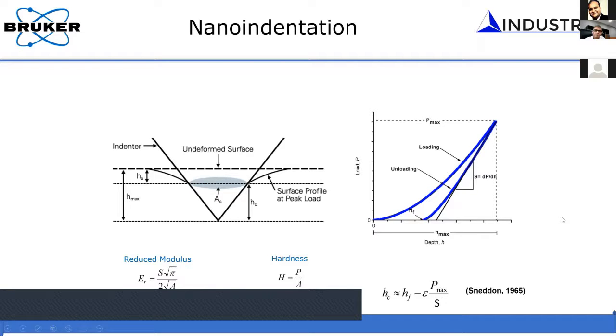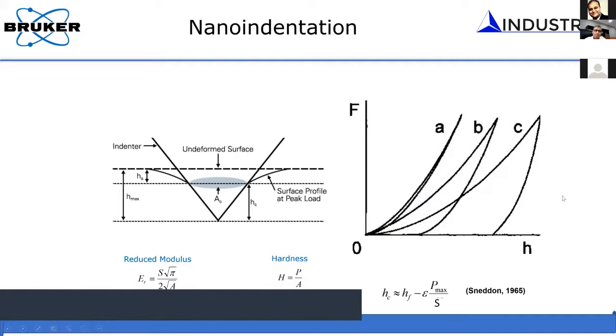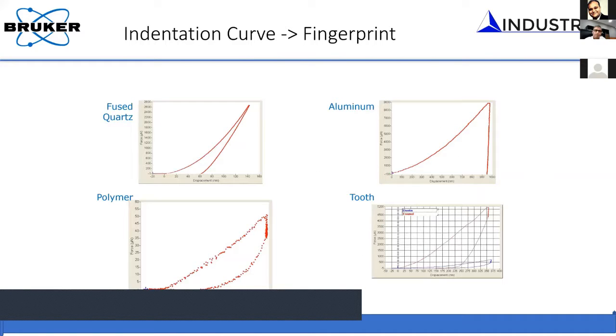By knowing the load you are applying, the stiffness that you measure for a given load, and the depth of indent and all of that. Okay, so if you have this load displacement curve, then you can do this hardness and modulus measurement. Like I said, it depends upon the material that you're studying. Some materials have more elastic behavior, some materials will have more elastoplastic behavior. So depending upon the material, it will have a unique fingerprint. And that's how we can use this technique to identify failure in materials, structure property correlation, and things like that.